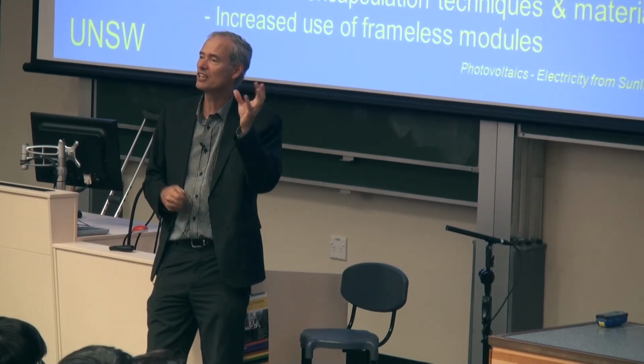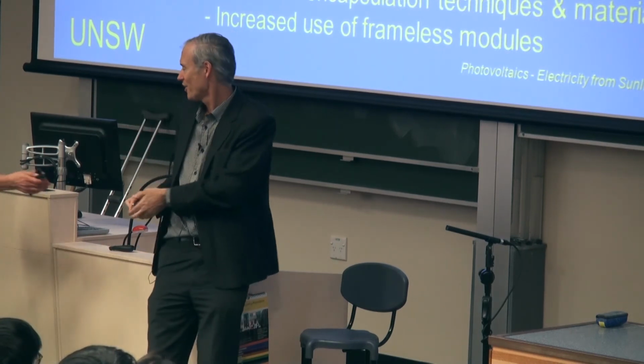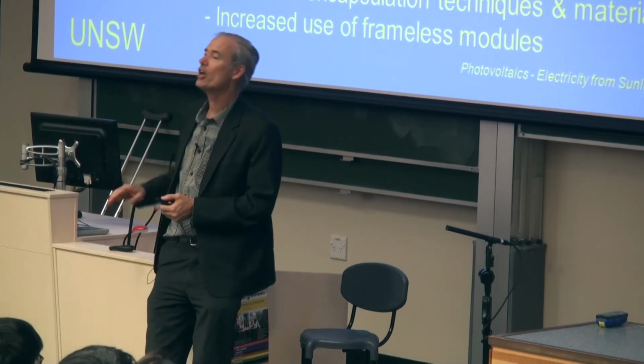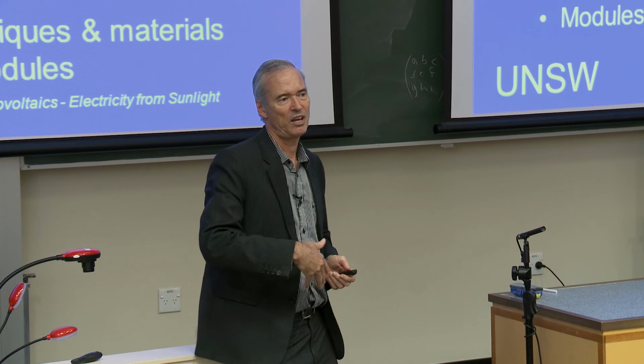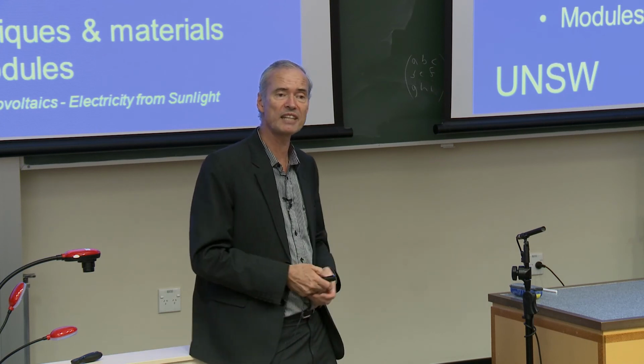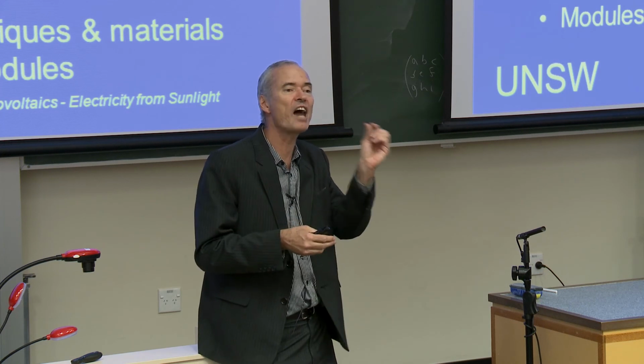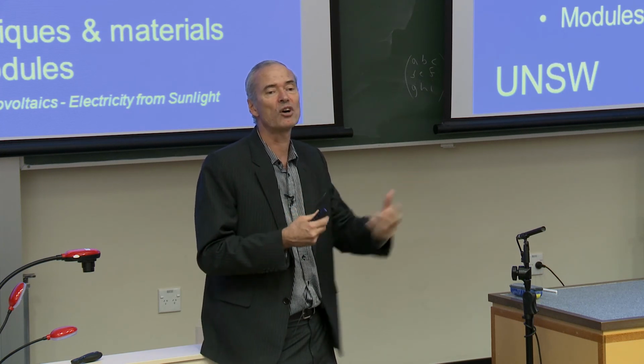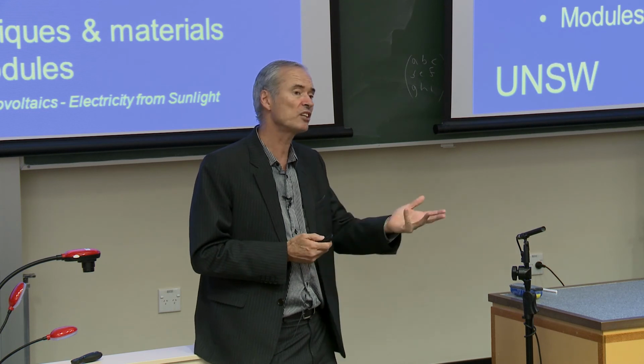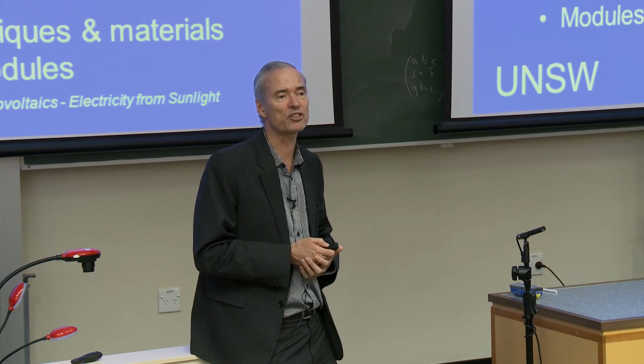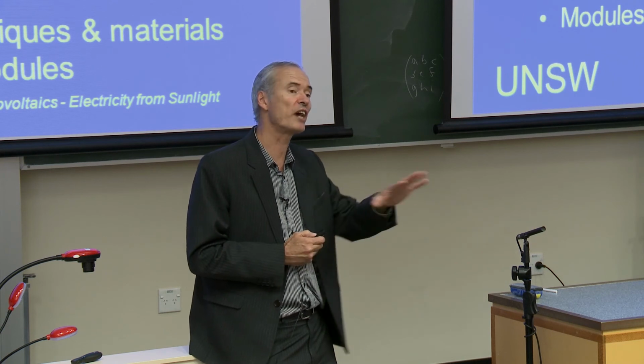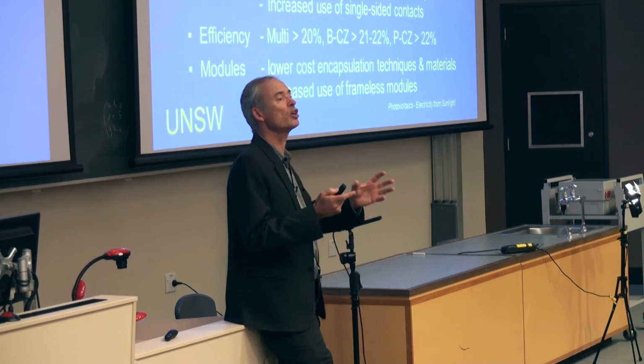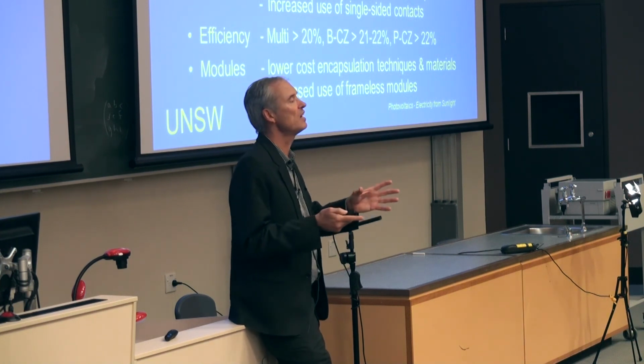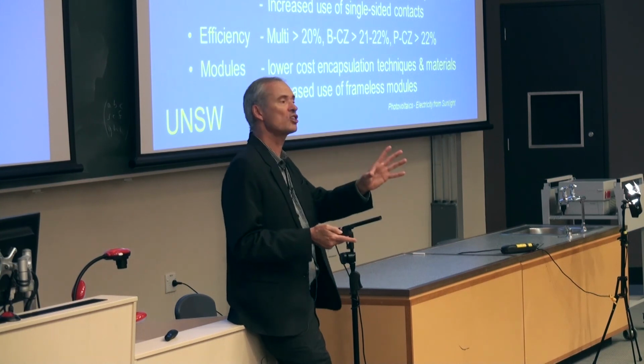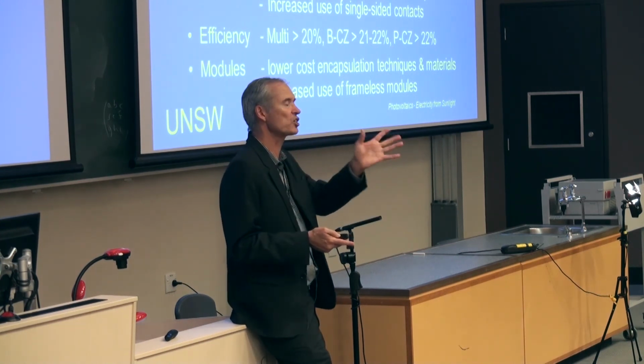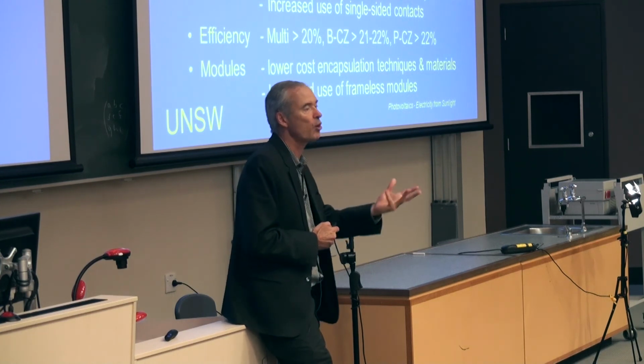See, silver's easy. You can just grind it down into a powder, turn it into a paste and just screen print it. And there's been a lot of good development take place with screen printed technology. They're able to screen print the lines narrower and narrower with better and better conductivity, etc. So it's a good technology, it's doing well, and it's still dominating in manufacturing. But you can't do copper the same way for a range of reasons which I won't go into now. And so alternative techniques have to be developed for depositing the copper. And some great technologies are being developed at this university and in conjunction with some of our industry partners to make it possible to do that.